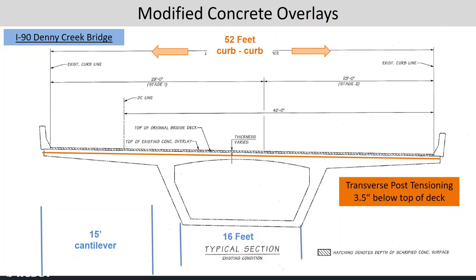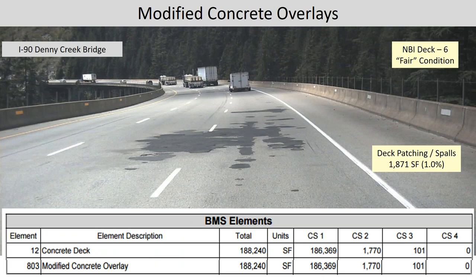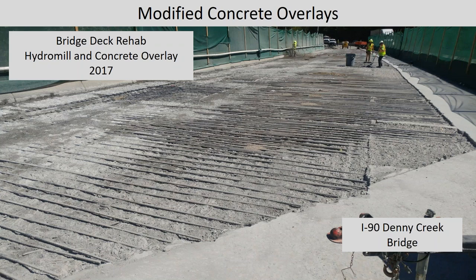It also has a unique feature where it has transverse post-tensioning. So it's really important to preserve this bridge because if anything happens to that transverse post-tensioning, it would be very costly to rehabilitate this bridge. So we were starting to see quite a bit of patching done by maintenance in the overlay. We were concerned it was getting down into the deck, so we programmed this for rehabilitation. And this is what happened.